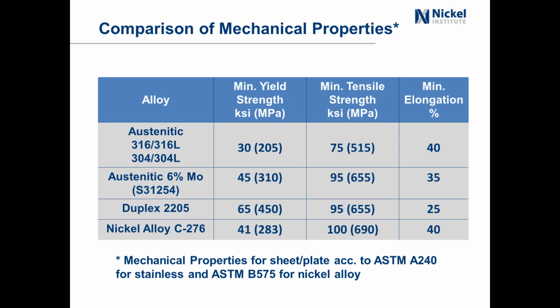So it's double the yield strength in comparison to an austenitic stainless steel or a 304. So you can build equipment, you might be able to use thinner material to achieve a lighter fabrication, maybe reduce the cost a bit. And then you had asked about the Hastelloy. So here's nickel alloy C276, eventually Hastelloy C276. The yield strength is 41 and the minimum tensile is 100. It's just a real mishmash of alloying elements, chrome and nickel and molybdenum, and so it's just solid solution strengthening, and so it's a bit higher than an austenitic stainless steel.